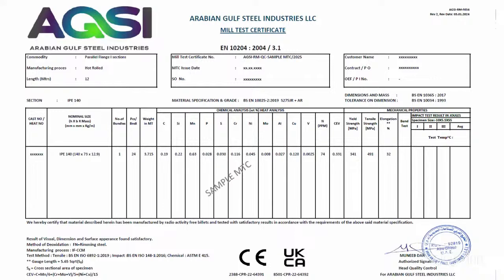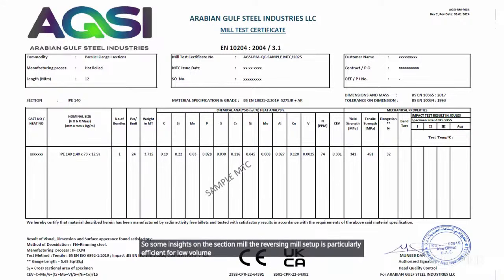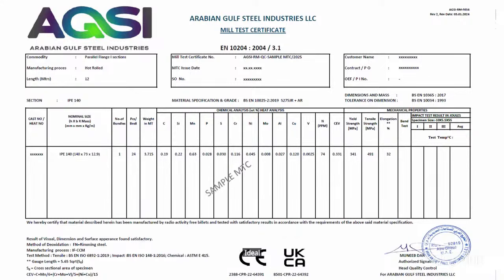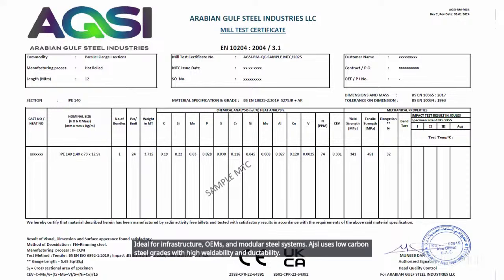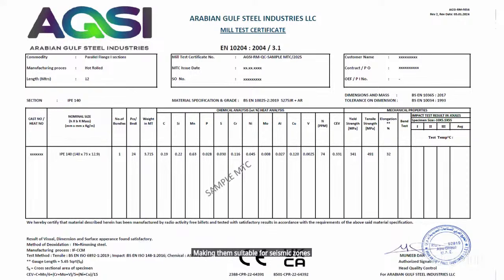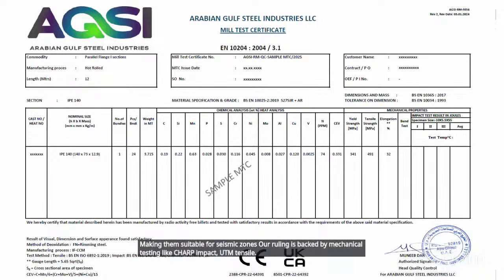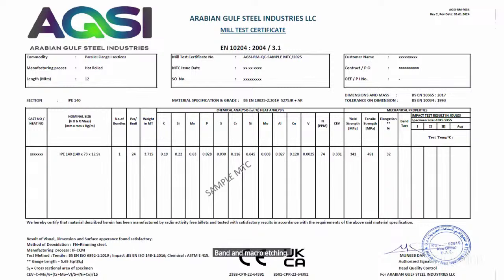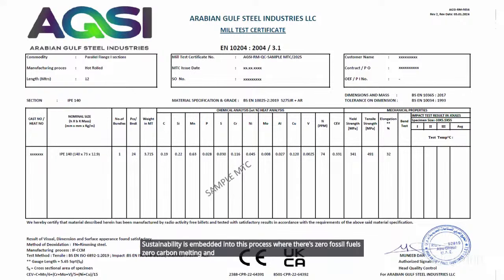So, some insights on the section mill. The reversing mill setup is particularly efficient for low volume or custom profile production, ideal for infrastructure, OEMs, and modular steel systems. AGSI uses low carbon steel grades with high weldability and ductility, making them suitable for seismic zones. Our rolling is backed by mechanical testing like Charpy impact, UTM tensile, bend, and macro etching to verify grain structural integrity. Sustainability is embedded into this process, where there's zero fossil fuels, zero carbon melting, and energy recovery systems in the furnace.